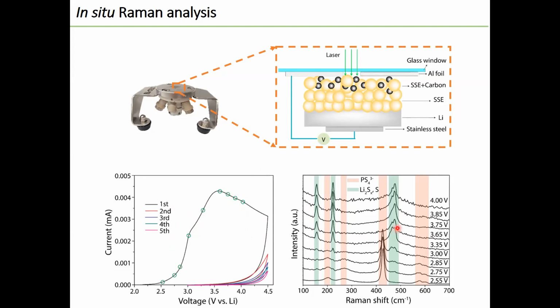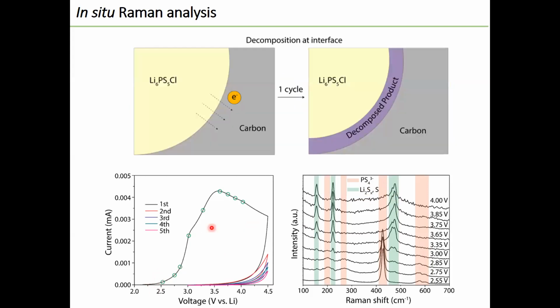Through the in situ Raman, we can see in the beginning all the PS4 peaks belonging to our electrolyte gradually disappeared, and there are some newborn peaks that appear, which can be attributed to lithium sulfide and sulfur. Through the in situ Raman, we further confirmed the electrochemical stability window of our electrolyte.